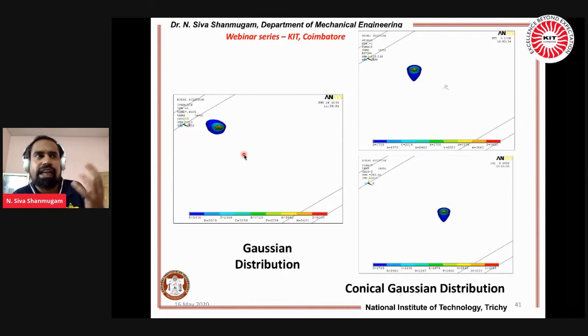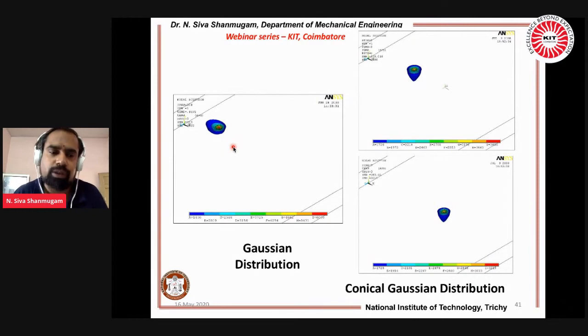It will not showcase anything with respect to the thickness of the material that is available here. To check the capability of the code that I have written using APDL, to ensure that I have fed both heat source models to find out the temperature profile. Only with the Gaussian you are getting a temperature distribution on the top surface, but when you are using the three-dimensional conical Gaussian volumetric heat source, I can get the temperature distribution on the top surface and also in the thickness direction.